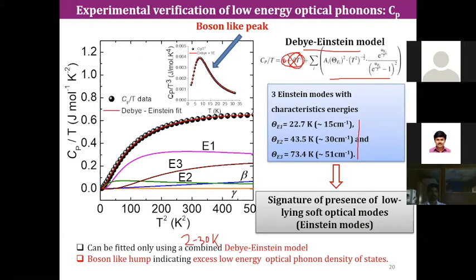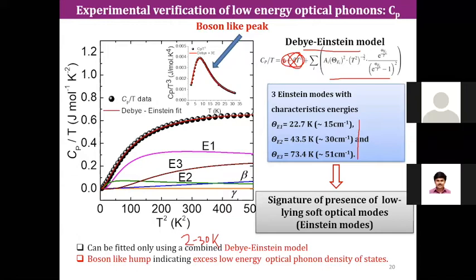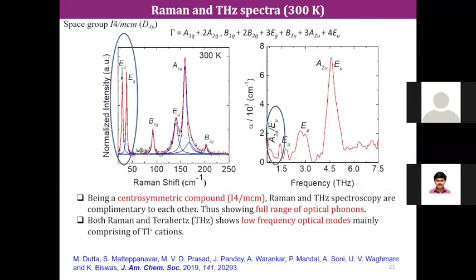And then once we plot Cp by T cubed versus T, we can see this peak-like feature in the experimental data, and this peak-like feature gives an indication of the boson peak, named after our famous scientist Satyendranath Bose. This is observed in disordered glasses, and this is the excess optical phonon density of states, which comes from the thallium rattling, and which gives rise to the optical acoustic coupling and lowers the thermal conductivity of a material.